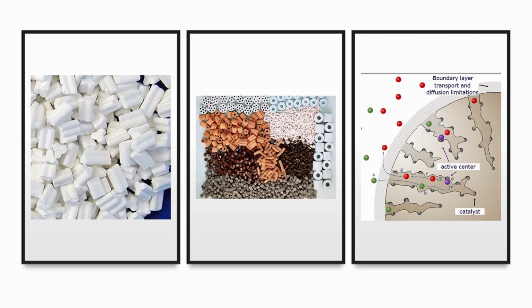However, this ratio will also affect acid strength. Accessibility of active sites demands control of porosity. Porosity of the solid catalyst is the key for the rate of mass transfer of reactants to and products from the active sites, which can affect activity via diffusion rate, selectivity because of the extent of secondary reaction, and stability via coke formation. Depending on the application, macroscopic catalyst bodies differ in size and shape.